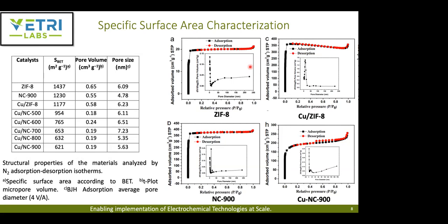So you have a mixture of both micropores and mesopores. So you have both high active sites and good mass transport. To confirm that, they need the specific surface area characterization. As we can see, the ZIF-8 they synthesized has about 1437 square meters per gram surface area, with a pore volume of about 0.65 cubic centimeters per gram. And the average pore size is about 6 nanometers. I think the average pore size is a larger number because they have a couple of macropores that make this number larger.